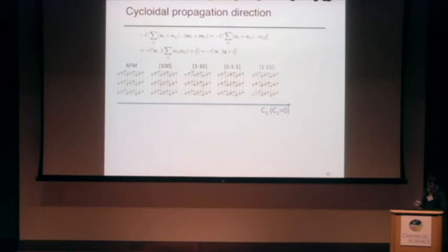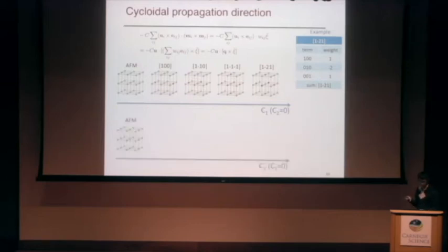us this Q vector. And the last one is the 1, minus 2, 1 cycloid. We still have six contributions, but along the y direction, the weight is doubled. So we have the weighted sum in this Q direction. And that's how it works for the first neighbor terms.